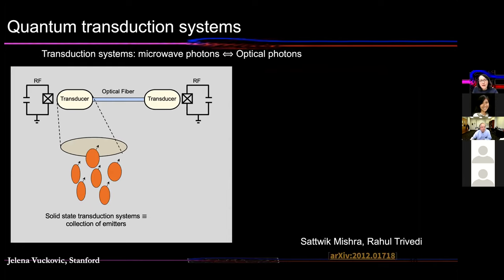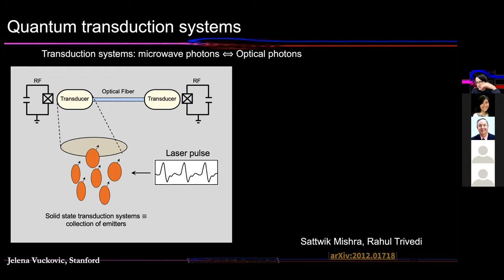For example, here, for a simple quantum transduction problem, where you are converting a microwave to an optical signal to interface quantum computers, superconducting quantum computers, via an optical network. Generally, the favorable approach is to use color centers or ions or atoms, typically in solids, and then drive them with microwave signals and optical signals and use that to convert microwave to optical signal. But because of inhomogeneities in atoms or ions, these transduction efficiencies are typically, in state-of-the-art experiments, 10 to the minus 5, 10 to the minus 6. That's the state-of-the-art result from, for example, Andrei Faraon's group at Caltech using rare earth ions in YVO.